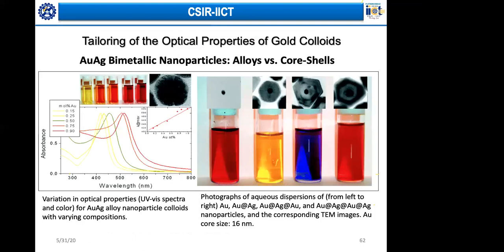So how do they actually influence? Here again, I'm coming back to optical properties because we can see and start to believe a change in their property. So here, these are only gold nanoparticles. And here, this is only an increase in the concentration of gold from 0.15 mole% to about 0.90. As you increase the concentration, here it is ions, here it is gold nanoparticles. And you can see that the intensity is increasing, but the red wine color is almost the same. That is what you get with one gold particle, and this colloidal solution looks red wine in color.